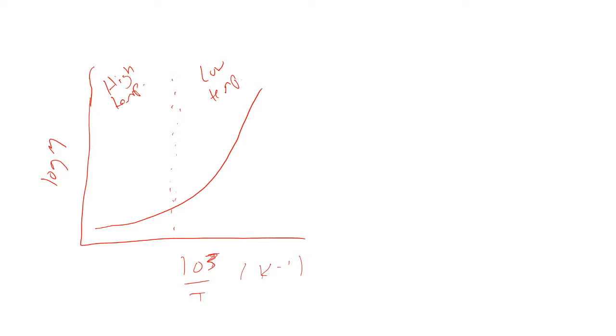Okay. So just a little background, right? Why the slope on the log plot? Because activation energy, it's an Arrhenius relationship. So it's proportional to e to the minus Q over kT.